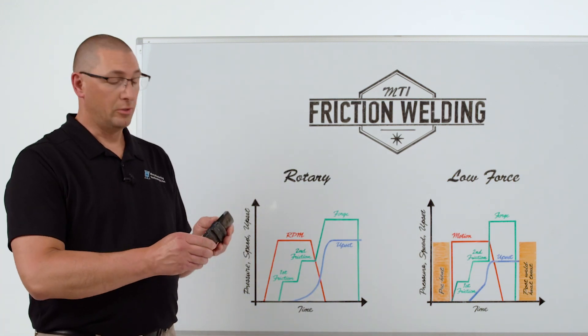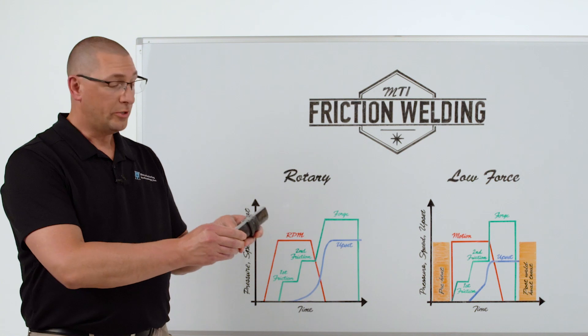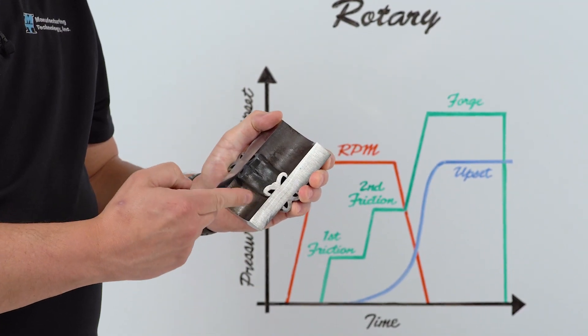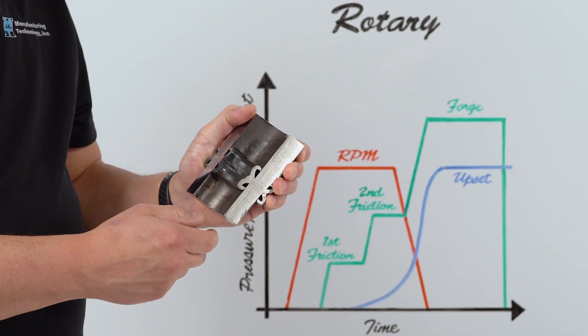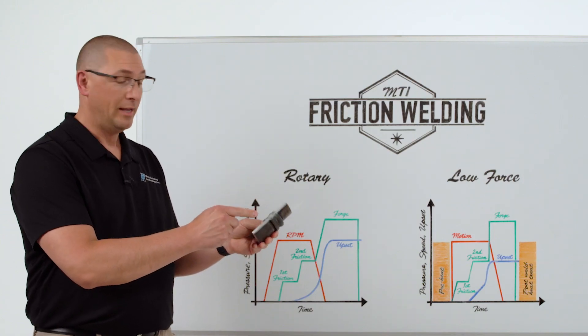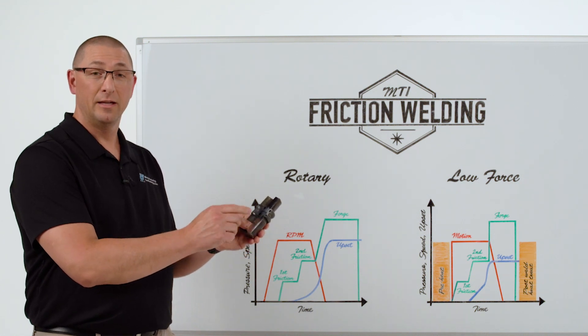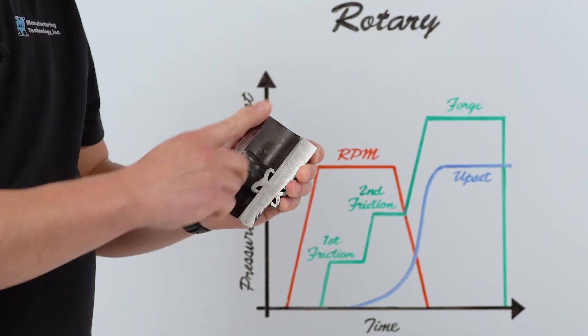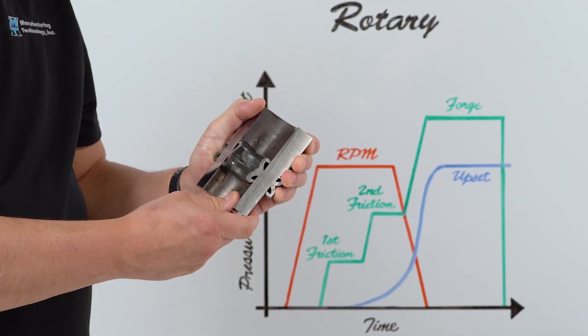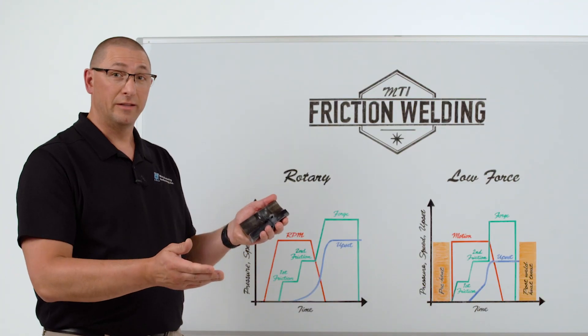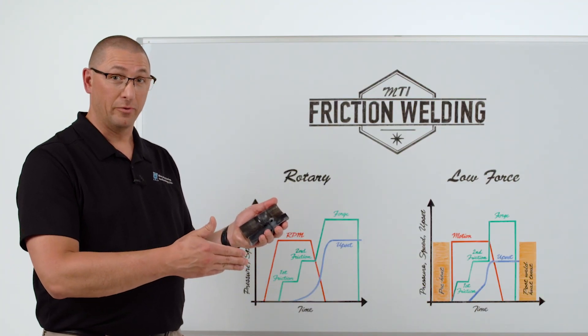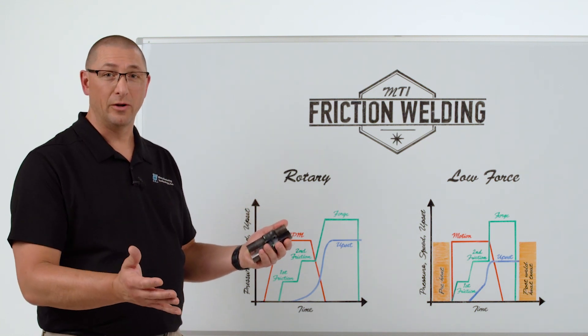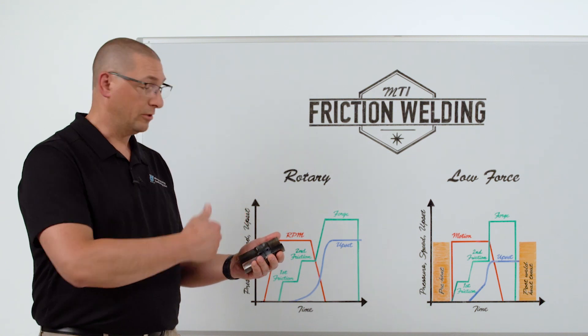If I look at a traditional oil well drill pipe component, you can see that there's a lot of upset with this weld. You can see the large flash curls. The flash curl is volumetric, so we have just as much upset on the outside as we do on the inside, but the inside space is much tighter, therefore the flash curl looks bigger. Many times we'll be shearing off this ID flash in the oil well application. In rock drilling, there's a gas lancing operation to remove this ID flash. So flash formation is one of the things that we design around with respect to traditional friction welding.